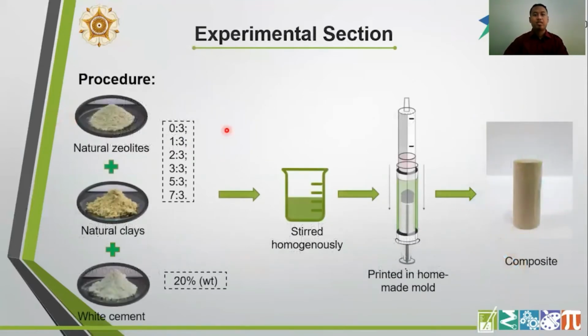To prepare the composite, 5 grams of a mixture of zeolite clay with a ratio from 0:3 until 7:3 was mixed with 20% of white cement and 4 ml of water in a glass beaker. The mixture was mixed homogeneously and printed using a homemade mold to be a composite.